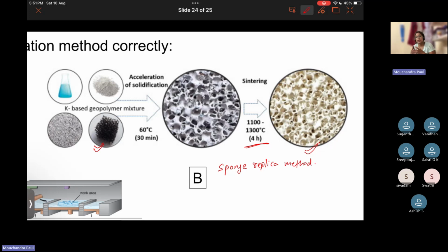We are using a polymer to create a mold that looks like a sponge, which looks like this. If we do close-up imaging, it would look something like this. Then we coat the entire sponge-like structure with our ceramic. You have to coat it very nicely and make sure the entire material is well penetrated within the mold. Then you heat it at a very high temperature. It will burn out this positive mold, and you will have a negative of your ceramic. Since it is heated at a very high temperature, it will get cooked, like you cook clay pots. This method is called the sponge replica method.